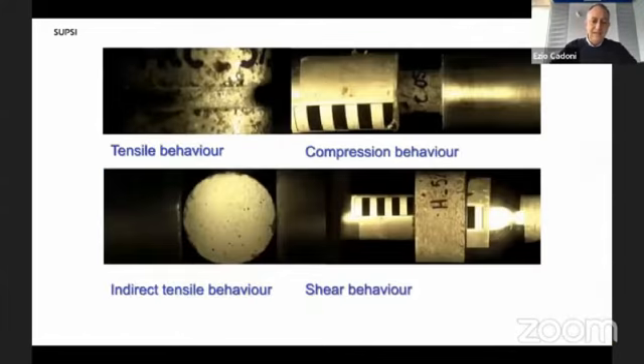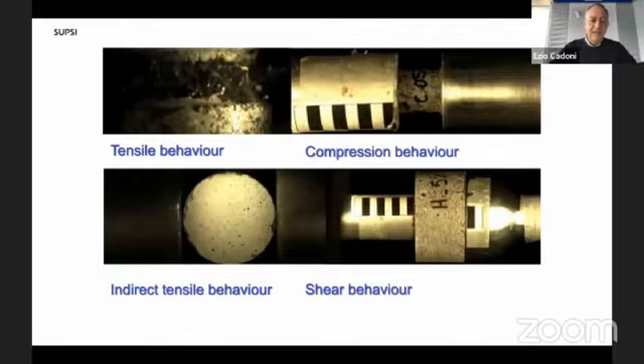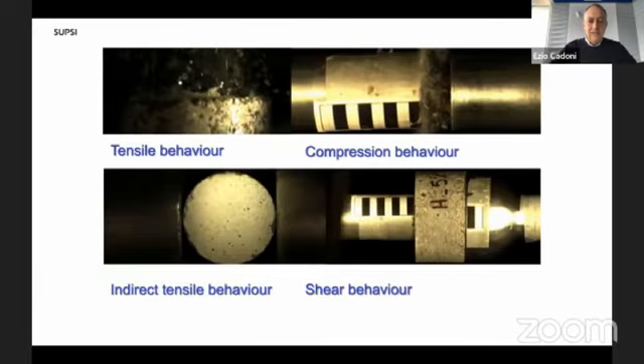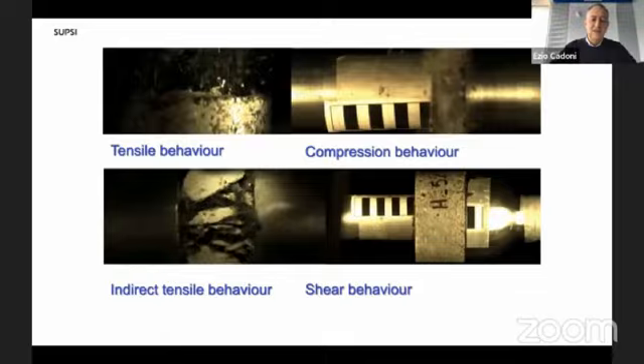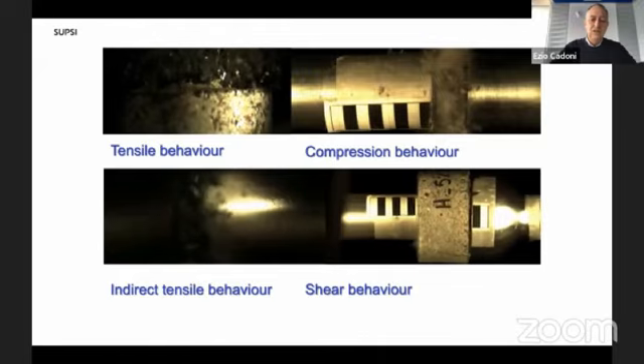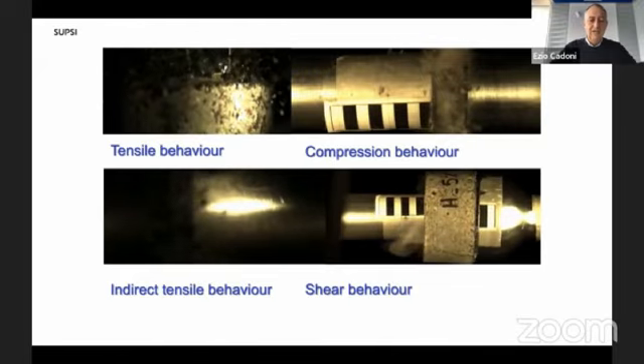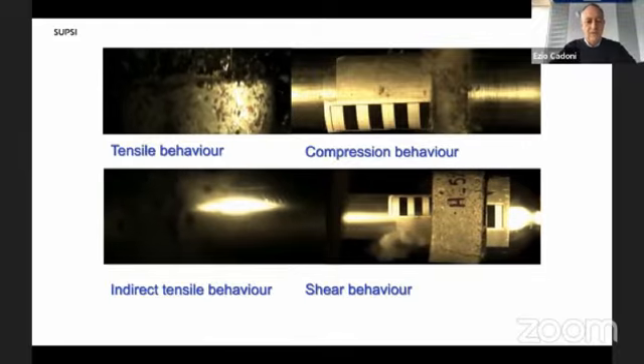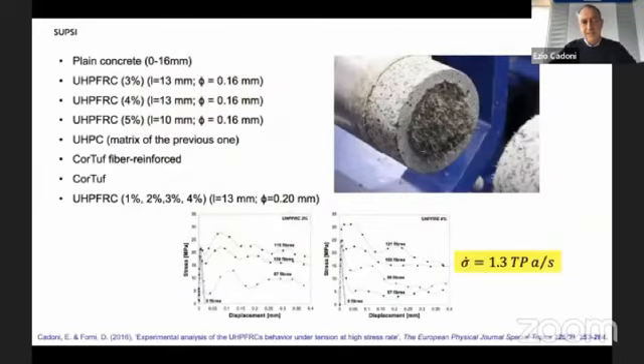The mechanical characterization at a high strain rate was performed in different loading modes, such as the direct tensile test, the compression, indirect tensile test, and shear, using samples having different shape, size, notches, and so on. We have analyzed several commercial UHPC having different fiber contents with different aspect ratios of high carbon steel fiber. And I'm going to present you some results on the high strain rate behavior of UHPFRC in compression.